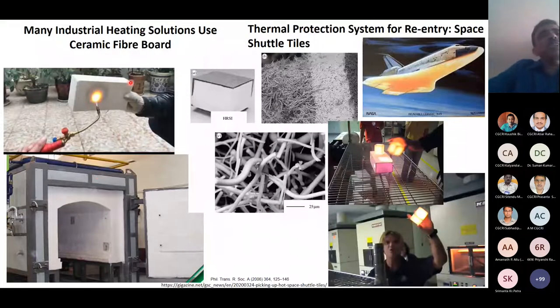For example, they can take very high temperatures. They can be used to make inner lining of furnaces, which are very light and can go up to high temperatures. Then fiber-based materials have also been used for making these tiles for the space shuttle. So the whole space shuttle is lined with these kind of tiles, which have these fibers. And these structures, these fiber-based boards, because they retain so much of air gaps, have very low thermal conductivity, which is what you want. So when the space shuttle re-enters the atmosphere, because of the frictional heat, it'll get very high temperature at the surface, but because it has exceptionally low thermal conductivity, it does not burn the metal or lead to total collapse or burning up of the metal structure.